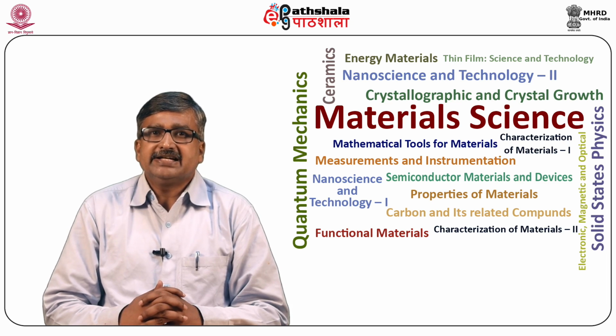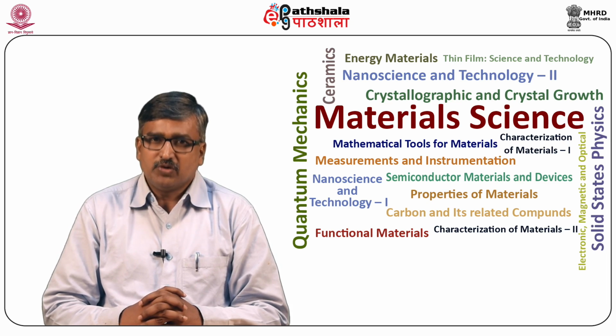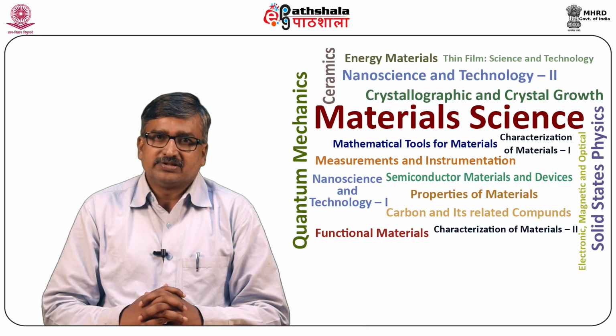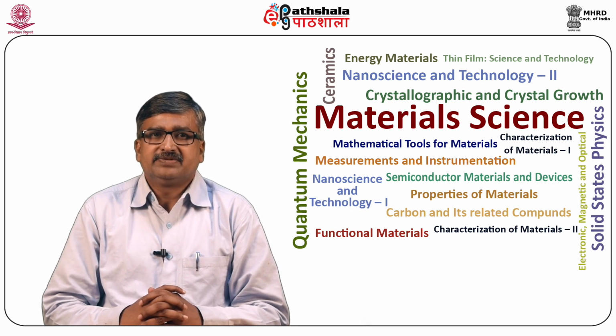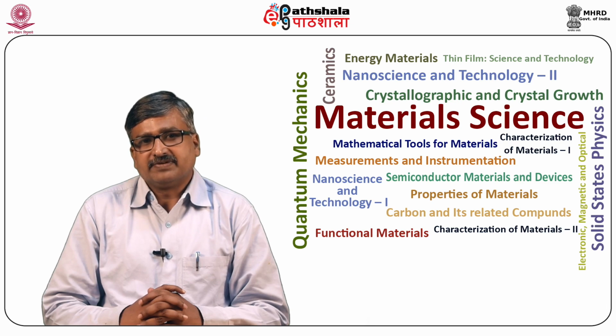These workers realized that nanoparticles with their defect centers might be oxidized more rapidly than the relatively perfect nanotubes, and they found that significant relative enrichment of nanotubes could be achieved this way.